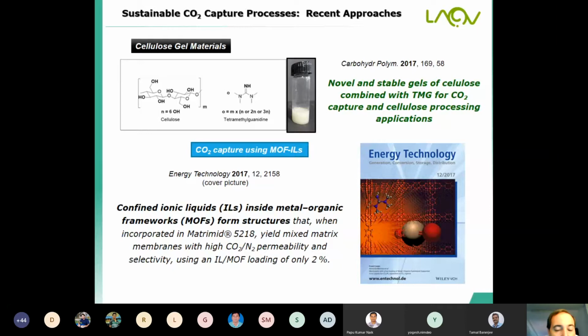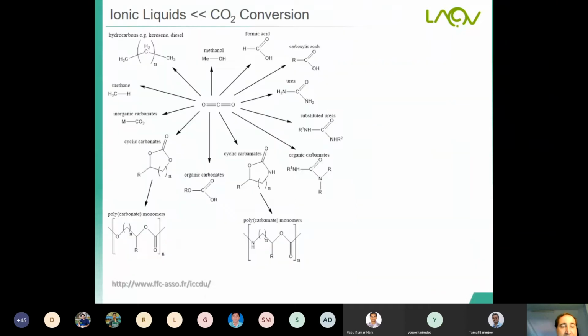And we are using only 2% of ionic liquid MOF loading. It's a very small quantity of ionic liquid and MOF, and we can obtain a very high selectivity for CO2. And this was the cover picture that you can see here in Energy Technology in 2017 related with this approach. It's well known that ionic liquids are very interesting to combine with CO2 for solubility, for adsorption, for different kinds of applications, but it's also interesting for CO2 conversion. It's possible to use ionic liquids for CO2 conversion to other products, including fuels.